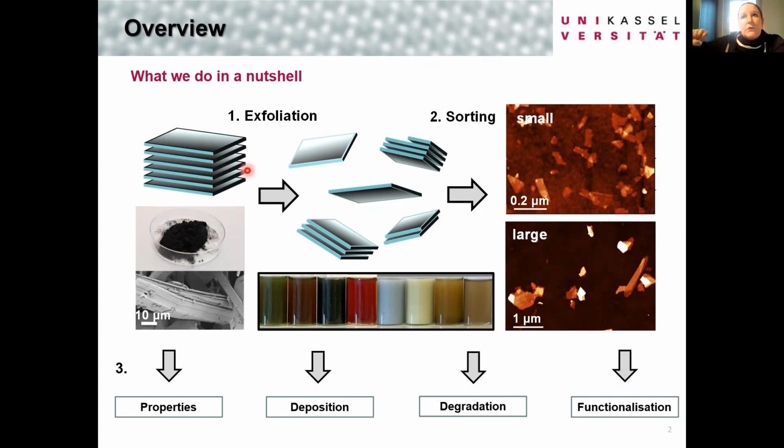So the idea is you impart high energy, and this will lead to mechanical exfoliation. For example, also involving shear forces that are randomly occurring in the liquid. However, as we will see, the exfoliation, so the peeling of the sheets, is not the only process that happens. We will see that we also chop down the material in other dimensions. Nonetheless, we get these platelets, and when we know how to stabilize them in the liquid phase to prevent their reaggregation, we get these stable dispersions.